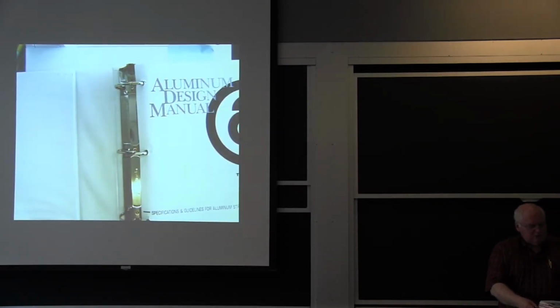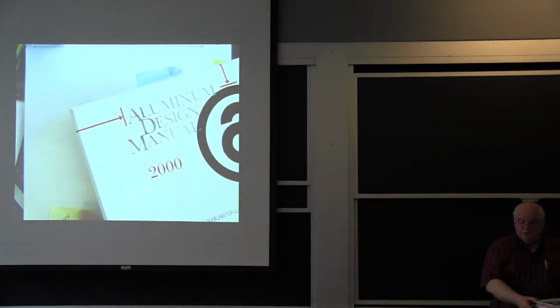The problem with aluminum is you get bigger residual stresses because you have more shrinkage. Steel shrinks 3.5% on solidification, aluminum shrinks 6%. So the stresses are greater. And aluminum also has 1/3 the modulus, and so it flexes more, and that creates problems. Did you have a question? Someone? No. Okay. So you have to pay attention to a number of factors, but the surprise for a lot of people, particularly Ford 30 years ago, was that when you weld it, you lose all your advantage of high strength. And that goes for aluminum as well.